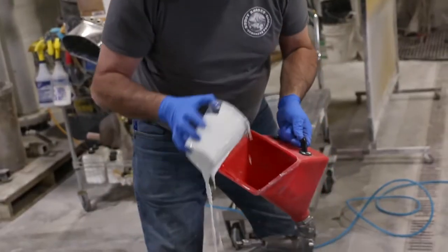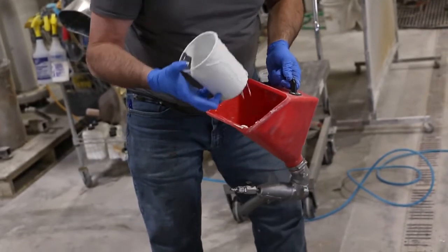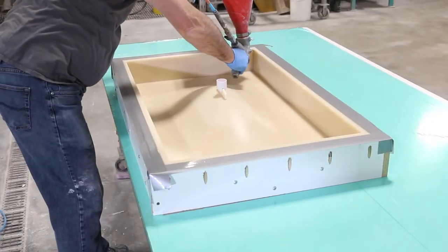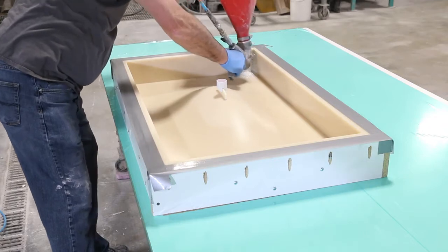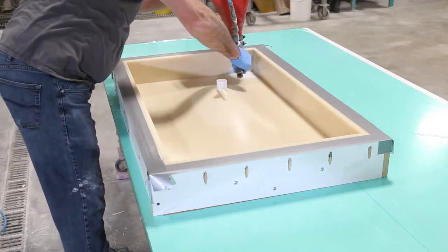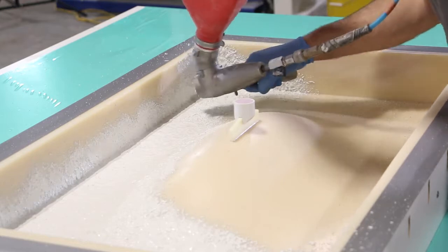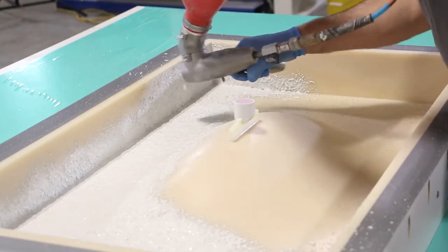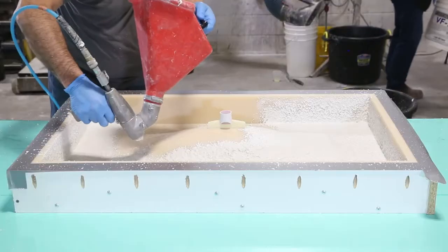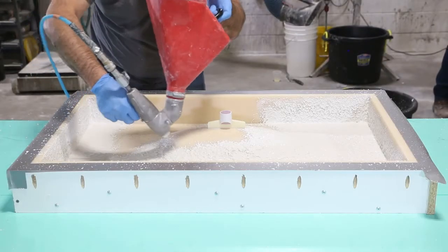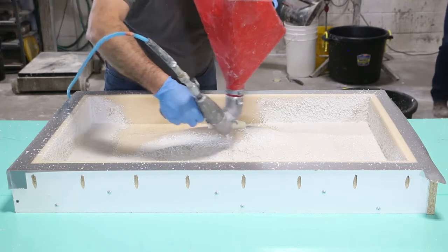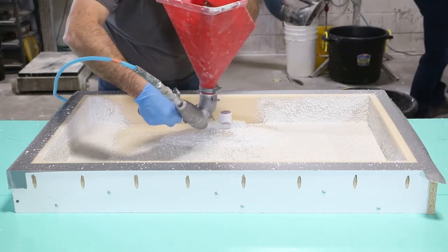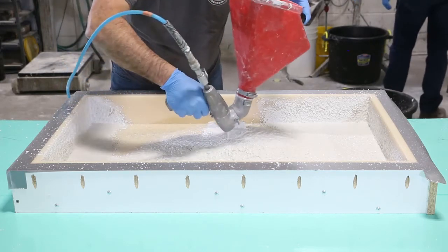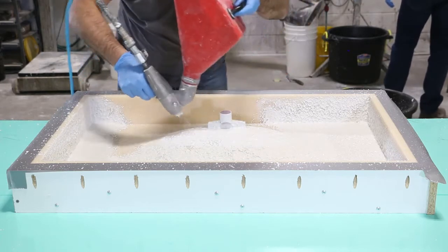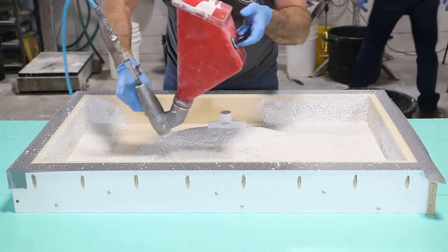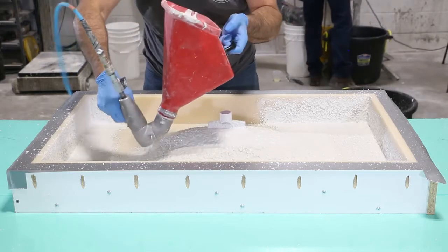Dispense the mix into a suitable hopper gun for spraying. Begin spraying into a corner while moving outwards, being careful to use the air from the hopper gun to remove collected sand in the adjacent corners before continuing. Based on the viscosity of the face mix, I adjusted the air pressure to allow the material to be deposited on the mold surface, but not so much that it breaks the mix apart, resulting in excess sand in the corners. As you see, material appears to drip from the nozzle. This material becomes blended with the sprayed material as I pass over the mold surface.